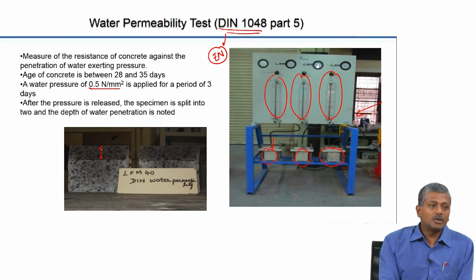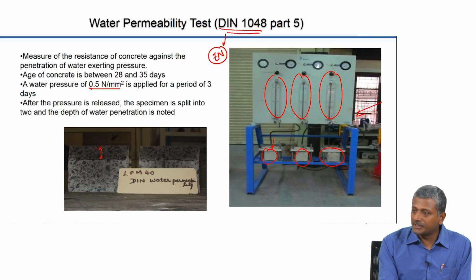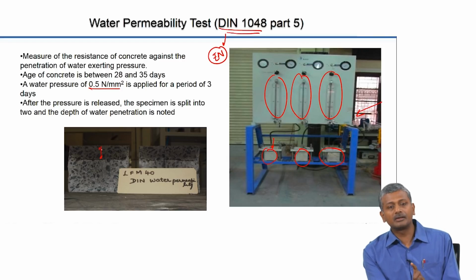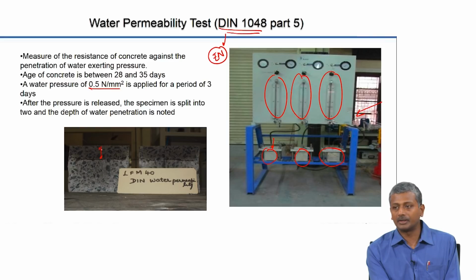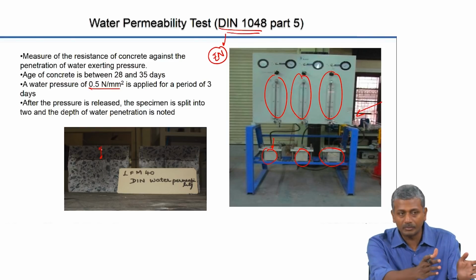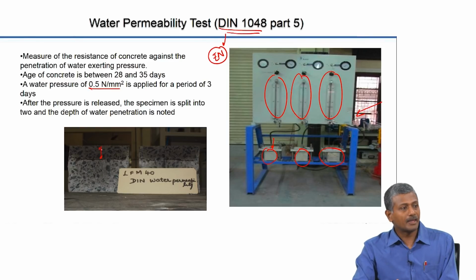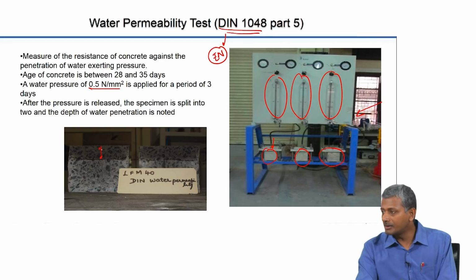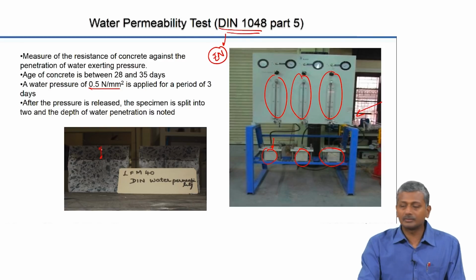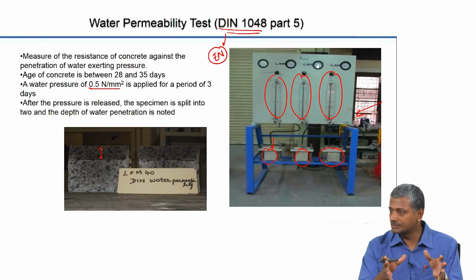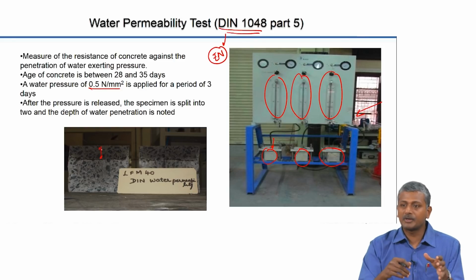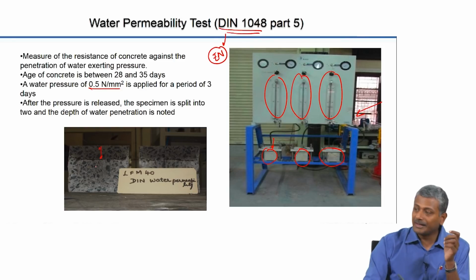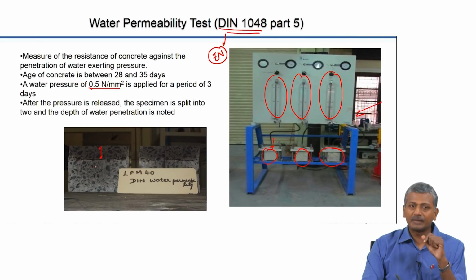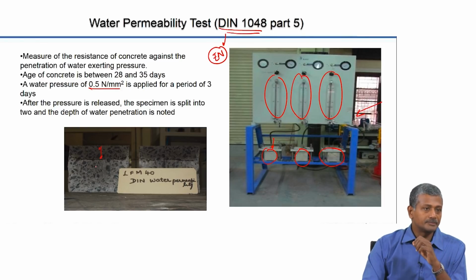Now, one thing you need to understand is this test method does not call for a particular conditioning of the concrete sample to be done. That means the concrete should be directly taken from the moist curing and subjected to this water penetration. Sometimes what may happen if the concrete is of a poor quality, that after moist curing, your entire concrete is totally saturated, right? Now, when you do the permeability experiment, it's very difficult to actually get a clear idea about the depth of penetration when you split open the concrete.